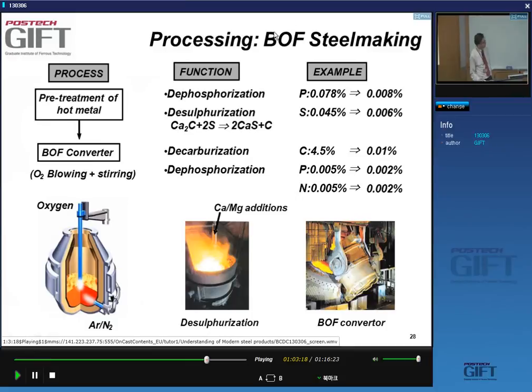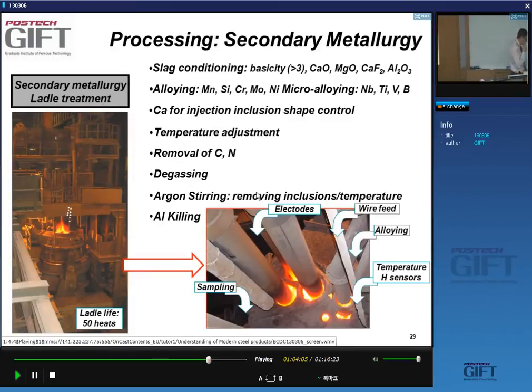Right. So let's go back to our basic oxygen steel making. So we have the process, the pretreatment of hot metal, the converter, and the end result is that we have material with very low phosphorus, 0.008, very low sulfur, 0.006, carbon 0.01, 0.002 and 0.002 nitrogen after the basic oxygen furnace. These very low levels of carbon, of sulfur, of phosphorus, we're quite happy with that.